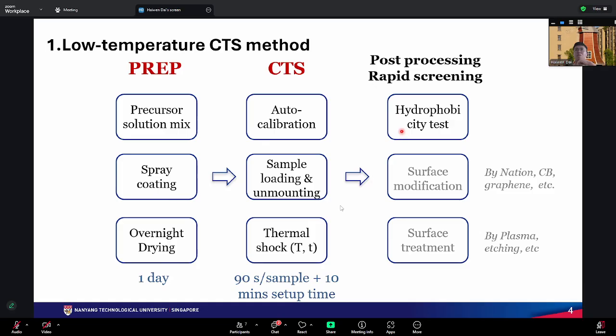After that, we quickly do a hydrophobicity test to see whether the sample is hydrophobic, to prevent flooding, where the electrolyte penetrates through the catalytic sample into the gas chamber. If this is okay, we think the sample is more likely to work for the ECO2 reduction test. However, at this stage we will be slightly more cautious, because all this experience comes from previous processes with magnetron sputtering and spray coating, where people did not have direct material synthesis in the material preparation. Here we have direct material synthesis in the preparation loop. So we will need to waste a few more samples to verify that low hydrophobicity means low performance. We need to verify this in both the substrate cases and the copper cases, and hopefully also in the precursor cases, which may come a bit later.